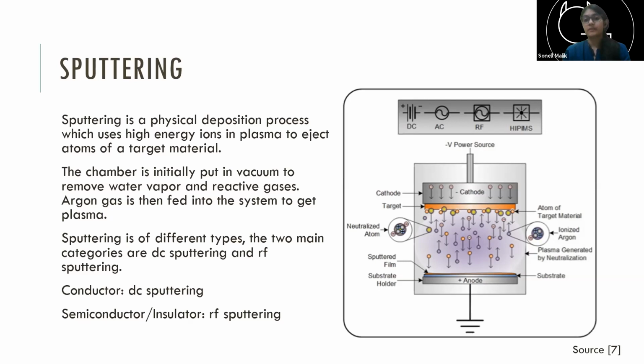Initially we put the chamber in a vacuum. We want to remove water vapors and any other gases that could possibly react with the material that we would like to deposit, because we also want no contamination for thin films. This is very important for thin films. That is why in most of the methods that I will be discussing here also, you need very good vacuum to get good concentration, and also so that your thin film is not contaminated.